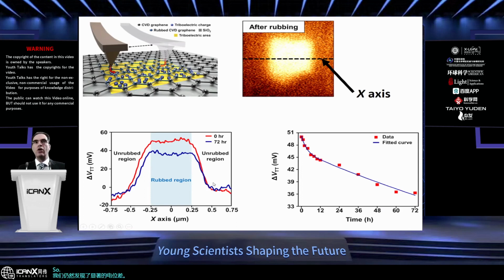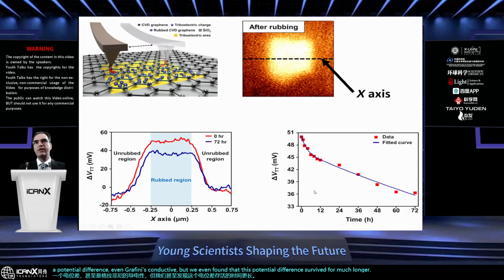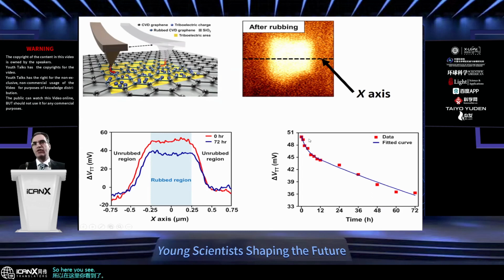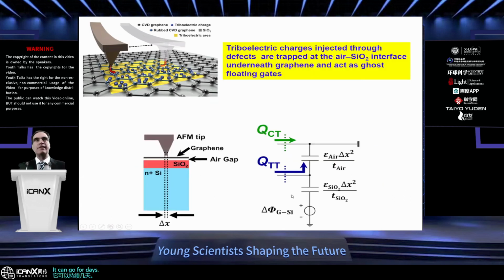So not only did we find a potential difference, even though graphene is conductive, but we even found that this potential difference survived for much longer times. So here you see the maximum potential difference as a function of time. Even after 72 hours, you see after an initial transient that is fast, there is a very slow transient, and it can go for days. So what happened?